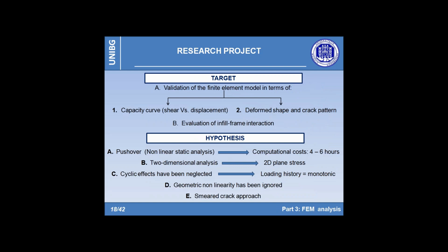The numerical analyses have been validated in terms of capacity curve, such as base shear versus interstory drift or displacement, and by comparing the experimental crack pattern with that predicted numerically, trying to simulate and investigate the interaction between infill and structural shear walls. All the tests have been described with a two-dimensional model using only plane stress elements.